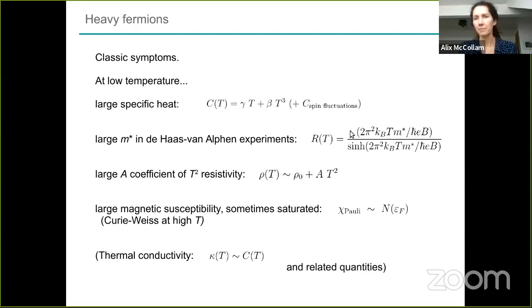This is the temperature damping factor from the Lifshitz-Kosevich formalism for the de Haas van Alphen effect, and the effective mass appears in here. So if you measure the temperature dependence of de Haas van Alphen oscillations or Shubnikov-de Haas oscillations, then you can measure the effective mass. And in heavy fermion compounds, this is very heavy. This is what gives the materials their name. The A coefficient of the T-squared resistivity, when there is a T-squared resistivity, so heavy fermions are